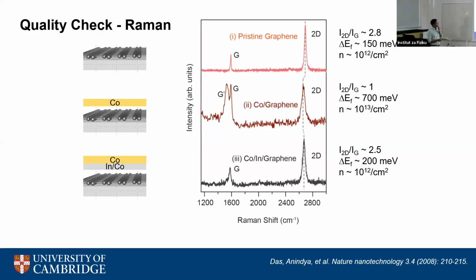So we can see that pristine graphene has a carrier density of 10 to the power 12, but when you deposit cobalt, the carrier density underneath the cobalt really increases, which makes the contact very conducting. This is bad for spin injection because the spins would scatter if there are a lot of carriers. But when we deposit indium cobalt, we can form a van der Waals gap, and the carrier density is very similar to pristine graphene because we don't have this chemical reaction at the interface, and the interface is quite clean. So you have kind of this vacuum gap.